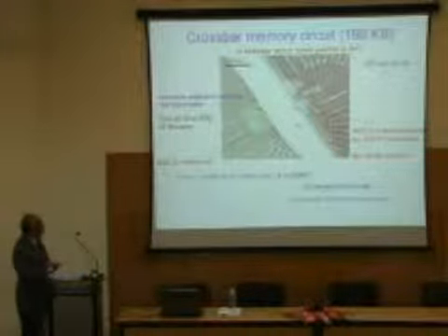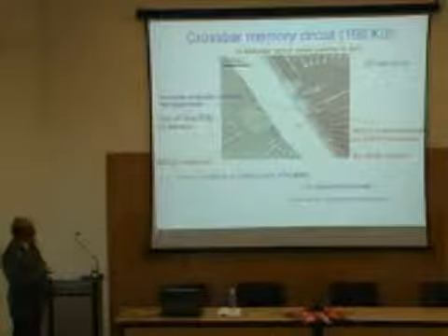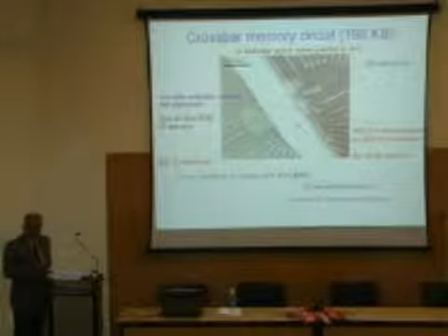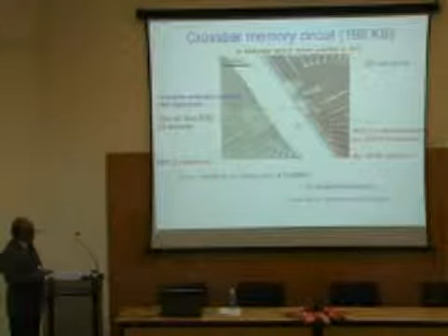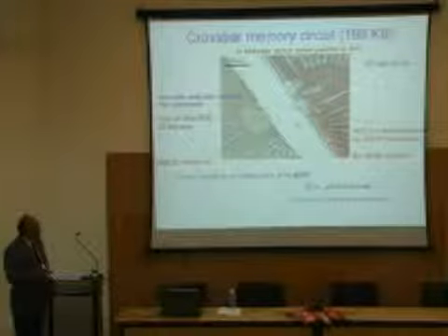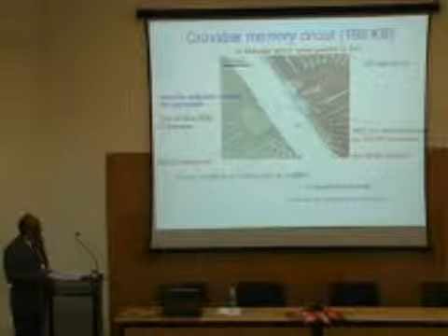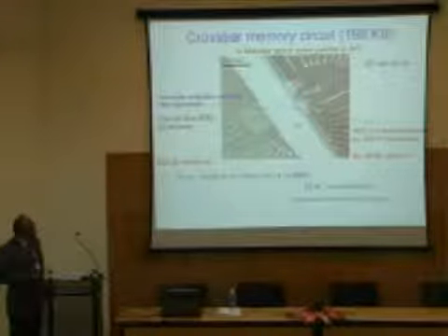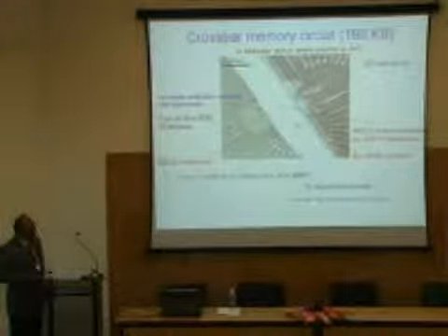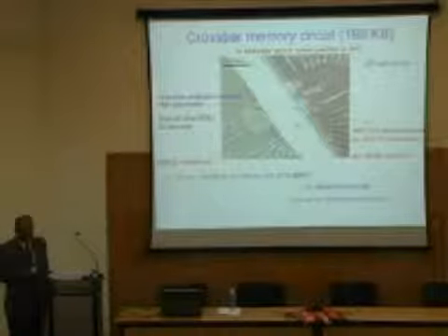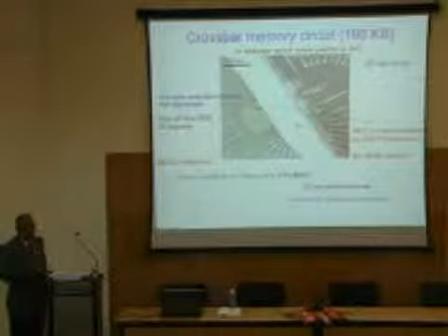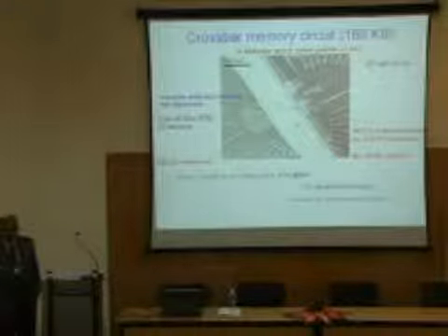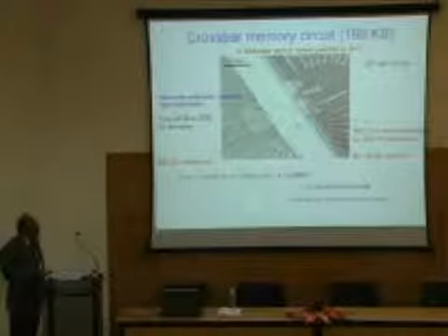And one of these is 1 bit, and they have been able to make a 160 kilobit device. In these devices, the distance between the wires is 33 nanometers. By conventional lithography, to achieve this is predicted for 2020. So this is a great jump in technology by the solution or molecular method. Okay?